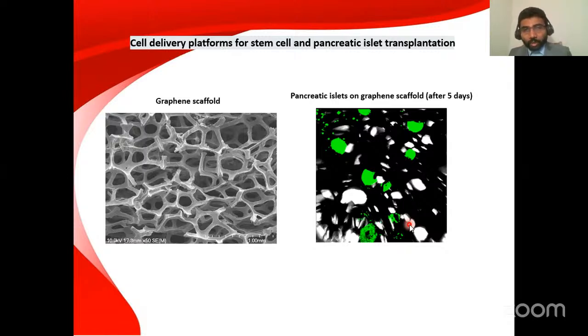And then that green colored thing that you can see is the pancreatic islets isolated from the mouse, which is growing very well after 5 days. Otherwise, it's very difficult to achieve such proliferation without a bioscaffold. And we also do stem cell transplantation in patients, and we develop clinically relevant collagen based materials for the transplantation of mesenchymal stem cells derived from bone marrow, umbilical cord, and various sources to the patients. So for that we develop scaffolds.